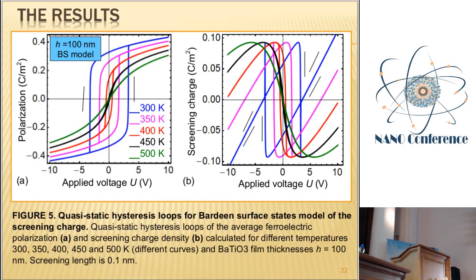For the Bardeen screening model, the linear model, this is the usual dynamics typical for the phase transition. We have a 100 nanometer film close to the critical thickness. Well, at room temperature, we see the loop because the screening charges screen some amount of polarization. It will be 1 micron without the screening charge and 100 nanometers with the screening charge here. Well, when we increase the temperature, the loop continuously vanishes, no double loops, no loop distortion, no horizontal shifts, and so on. At 500 kelvins, there is no loop at all. And the behavior of the screening charge is also conventional. We see a rhomboid shape of the screening charge for low temperature, and no hysteretic shape for higher temperature when the hysteresis of polarization disappears.